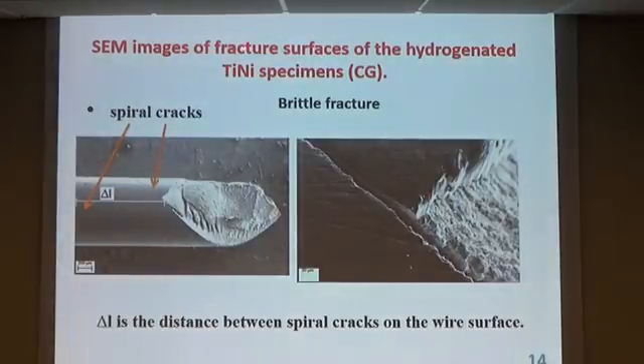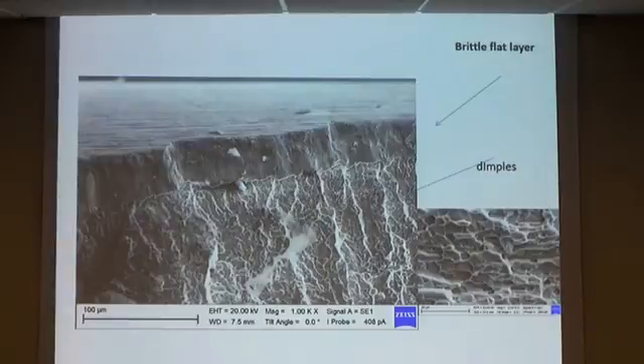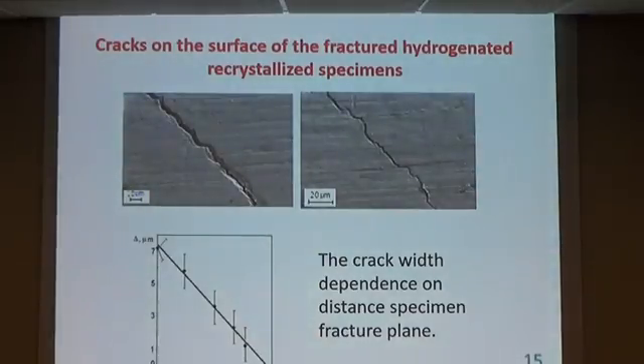It is an image of the fracture surface of hydrogenated titanium nickelide specimens with coarse grain structure. Brittle fracture, spiral cracks. Delta L is the distance between spiral cracks. It is a brittle flat surface. Cracks on the surface of fractured hydrogenated recrystallized specimens. Many cracks. Crack width depends on the distance of the specimen from the fracture plane.